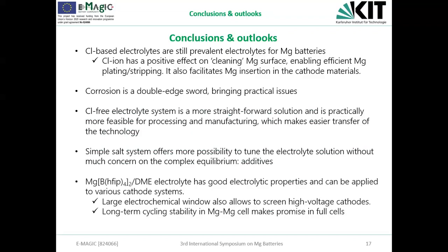As I have presented today, the magnesium borate electrolyte has good electrolytic properties and can be applied to various cathode systems. In the next step, we are trying to check the compatibility of magnesium insertion into high voltage cathode materials, because the advantage of the electrolyte system is that it could provide a large electrochemical window, and also we are pursuing a high energy system. Also, we hope that the long-term cycling stability in the symmetric cell could be transferred to the full cell system in the future, hopefully.